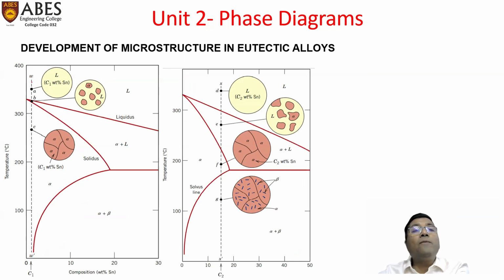So when we cool any of this composition from 380 or 350 degrees Celsius along this vertical dotted line, we have a complete liquid phase here, where a single phase would be present. Then at this point, both liquid and solid would be present. And then complete alpha would be present. It's a single phase alpha, and till room temperature only alpha would be present.